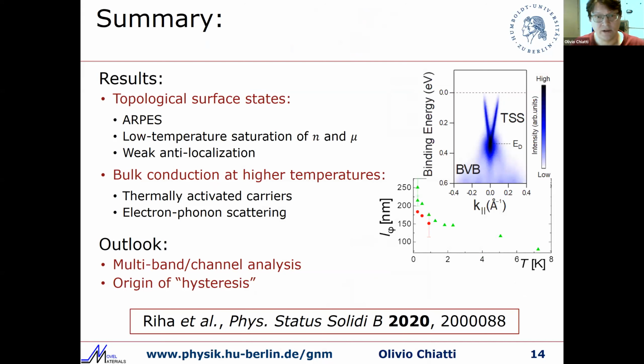And so to summarize, our measurement results indicate through ARPES, the low temperature saturation of the charge carrier density and the mobility, and the weak anti-localization that we have topological surface states. But at high temperatures, we can say also that we have a bulk conduction, which comes from thermally activated carriers into the bulk conduction band with electron-phonon scattering.